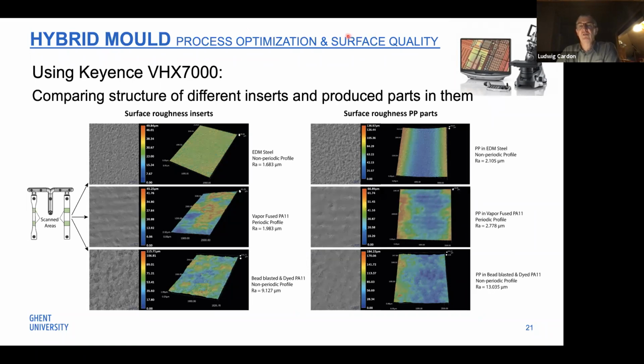And we look inside the surface quality by, for instance, in this case, we do it by contactless Keyence surface roughness measurement. So you see with the EDM steel roughness, the vapor fusing of a polyamide 3D printed insert, but with a special surface treatment. They also can treat the surface by bead blasting or dyeing. And you see the difference in the scope of the roughness. So this is also some investigation in combination with the morphology and flow behavior and cooling principle.